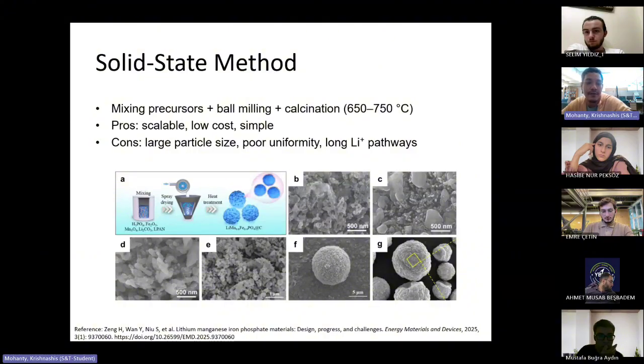First is the solid state method. As I said, we mix precursors, we ball mill, and the most important aspect of synthesizing LMFP is the temperature. The calcination temperature is a very crucial factor for making LMFP. If it does not reach the right temperature, it does not get calcined, or the particles stay dispersed, do not agglomerate, and do not reach their potential and do not carbonize. Anything below 650 to 750 would not be apt, would not make it crystalline, and would not help it attain the olivine structure. Anything above 650 to 750 may damage the structure itself, may dissolve the carbon source inside the material.